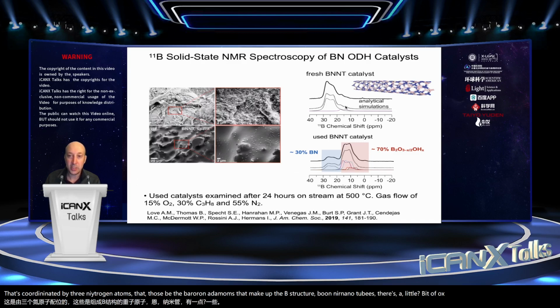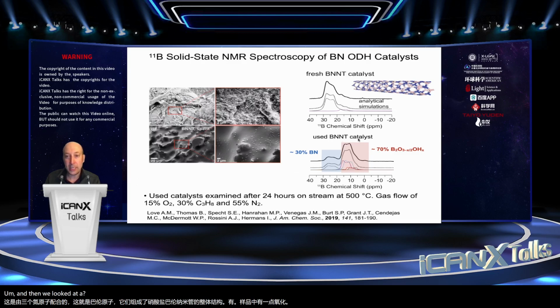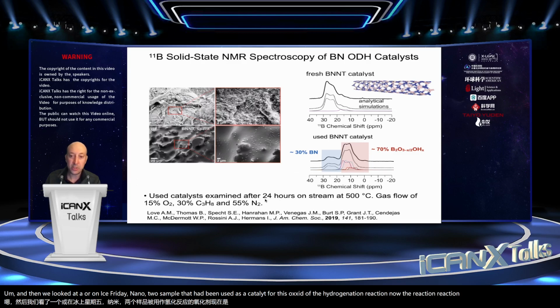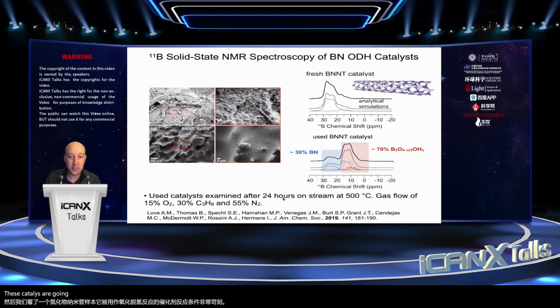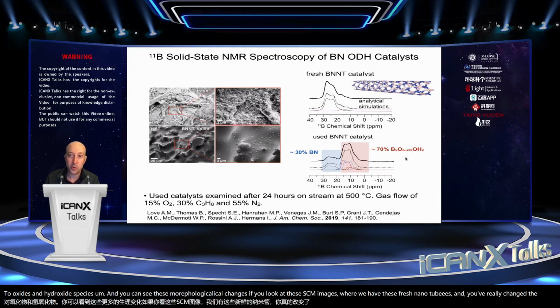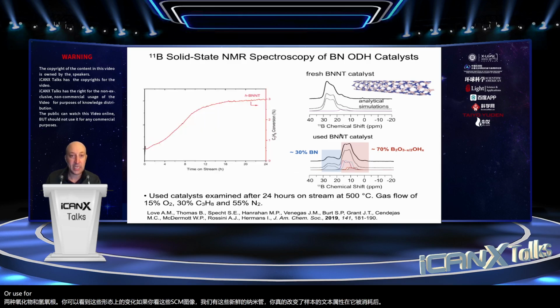There's a little bit of oxidation in this sample. And then we looked at a boron nitride nanotube sample that had been used as a catalyst for this oxidative dehydrogenation reaction. Now, the reaction conditions are quite harsh. These catalysts are going to be on stream for 24 hours at 500 degrees Celsius, subjected to gas flows of oxygen, propane, and nitrogen. So what we see is really interesting. If we just look at this boron-11 NMR spectrum, you can see that about 70% of the material has been converted from a nitride to oxides and hydroxide species. And you can see these morphological changes if you look at these SEM images where we have these fresh nanotubes, and you've really changed the textural properties of the sample after it's been spent or used for catalysis.